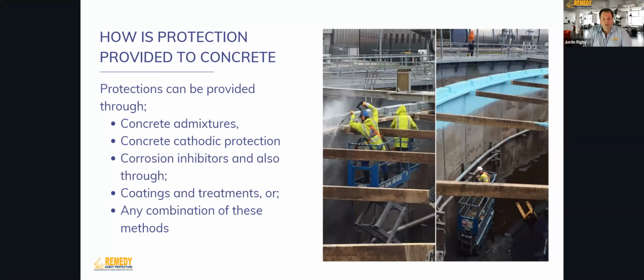Corrosion inhibitors can be applied within the admixture, but also later through migrating corrosion inhibitors. So it's a solution you put on the surface and it migrates through the concrete. And we can also use cementitious polymers to waterproof the surface. So they provide a barrier on the surface. So do our polymer coatings such as epoxies and polyureas provide a barrier to separate the contaminants from the concrete.